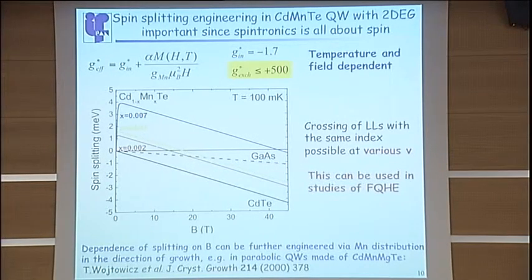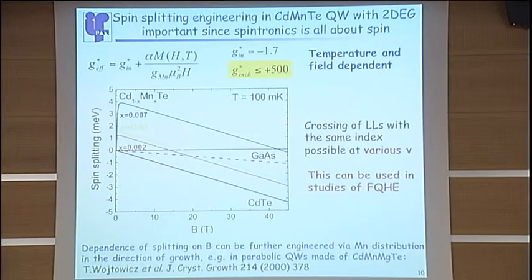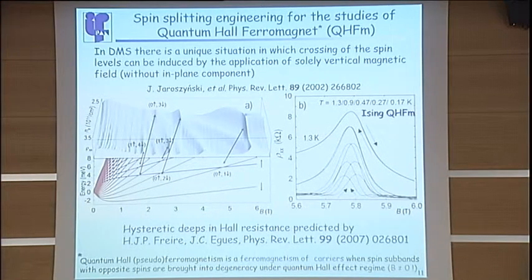Also, the dependence of the spin splitting on magnetic field can be further engineered by non-even distribution of manganese in the growth direction. So you can, for instance, produce quantum wells made of cadmium manganese magnesium telluride, and produce the required shape of the spin splitting. Also, we have already demonstrated, and by J. Jaroszyński, who is also at this conference, that those materials can be used for the studies of quantum Hall ferromagnet. It was many years ago that we observed the crossing of the Landau levels with different directions of the spin, so that if they are brought into degeneracy under the quantum Hall effect, ferromagnetism of carriers is produced. And the uniqueness of the system is that you don't need to apply an in-plane magnetic field to produce this crossing.